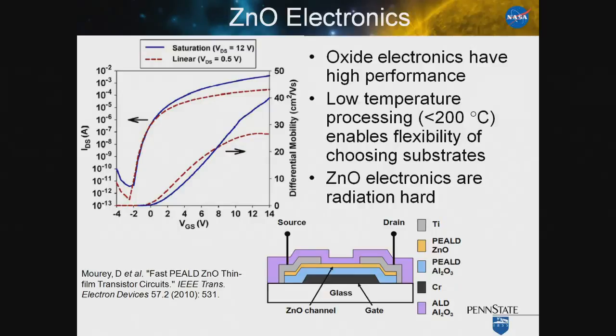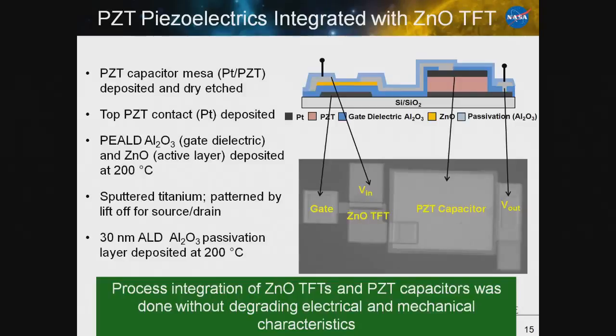And to investigate whether or not this would in fact be a problem, we have worked to prepare zinc oxide thin film transistors immediately adjacent to or directly on top of piezoelectric cells. I show here the typical cross-section and the material stack that are used in these thin film transistors. We typically, following preparation of the entire device, coat the entire surface with an aluminum oxide passivation layer deposited at 200 degrees C. And so we were able to do the fabrication.